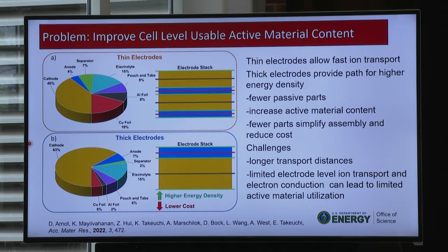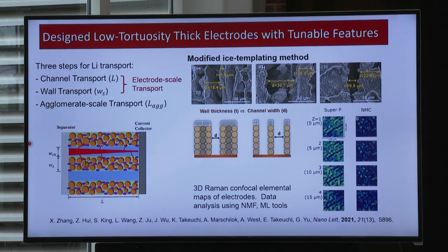So we've spent a number of years actually investigating the opportunities to design low tortuosity, thick electrodes with tunable features. So the opportunity for increasing cell-level energy content can go up, and it's a balance between porosity and energy content, because if it's too porous, then you're also not effectively using space.